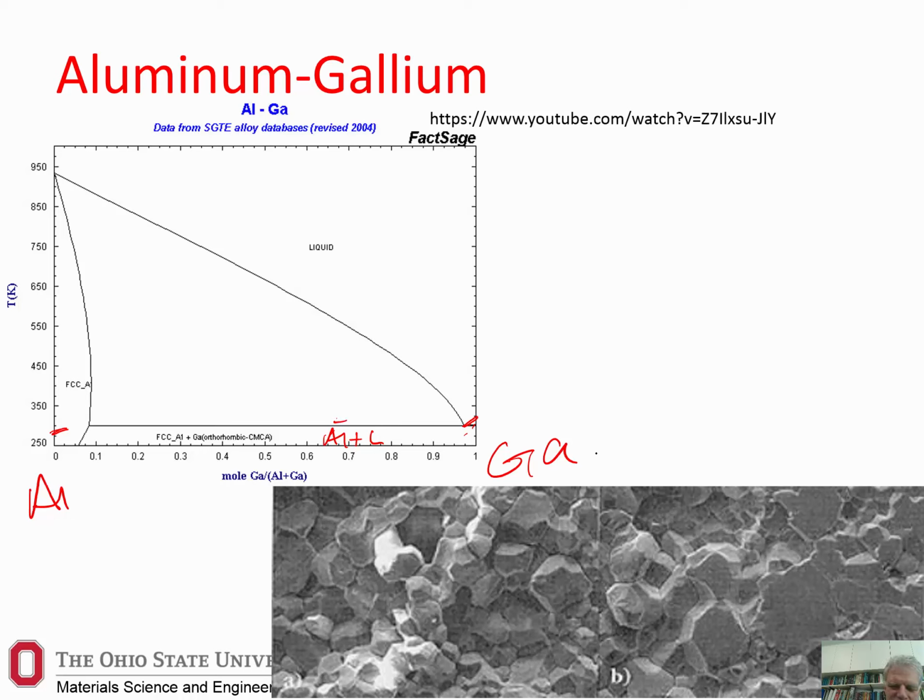And so if you have just a little temperature, you can end up with aluminum plus gallium there. And the gallium can be weak or liquid, and that can go along grain boundaries and embrittle it. If you're over here, you can have just a small amount of gallium that's present, and possibly in the liquid phase it tends to segregate along the grain boundaries, and it's a way you can actually cause aluminum to fail along the grain boundaries. Each of these are grains, they're crystals, and this can be a bad thing.